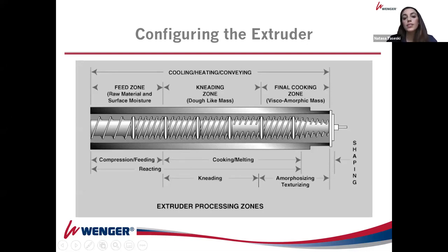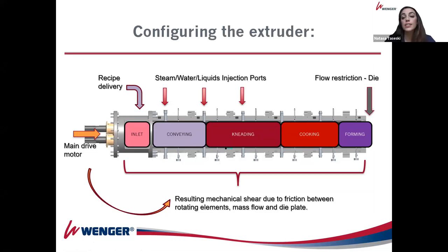So if we look at what happens in configuring an extruder for dry texture proteins, we have dry recipe delivery at the inlet here, and then addition of steam, any other liquids or water into the system, wherever applicable and dependent on what ingredients you're processing. So the material just gets into the extruder barrel and then gets quickly conveyed away from the inlet towards the kneading and cooking zone. So the raw material gets compressed as it goes through the extruder and it gets exposed to heat and pressure and shear and finally gets into a melted state before it reaches the die where you get the final forming of your product. So basically, due to shear and friction within the extruder, you're cooking the protein.